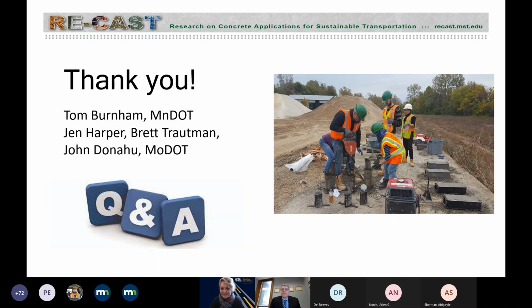Okay, so hopefully that answered the question. The next one here is a little bit long. It's a few questions in a row. What was the percentage compaction measured in the field after the rollers? Also, was the density measured using direct transmission down to at least 75% of depth? It doesn't appear as though the small roller was enough to get proper compaction through the entire depth, as shown by the field saw cut samples. Is it recommended that the proper roller is used to achieve compaction through the entire depth of the pavement?